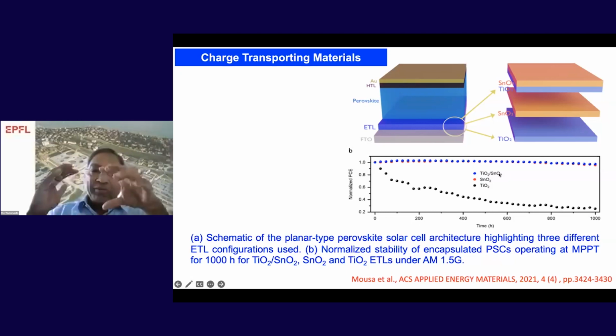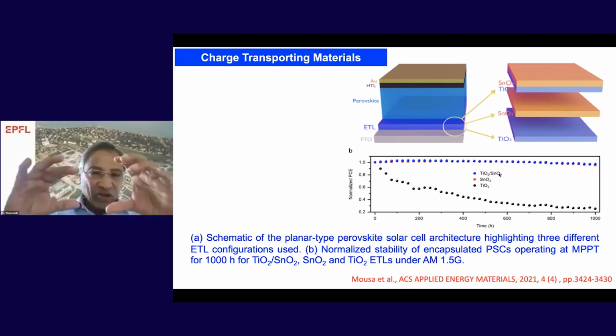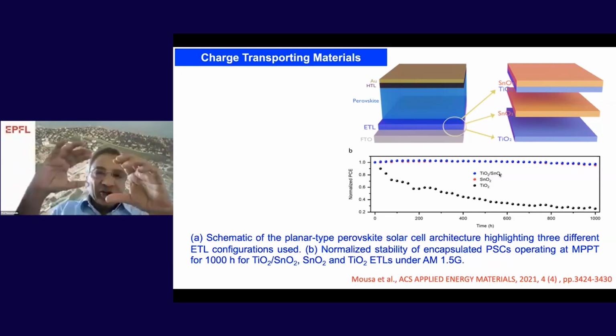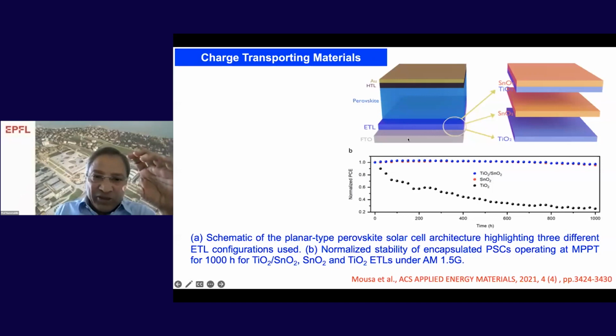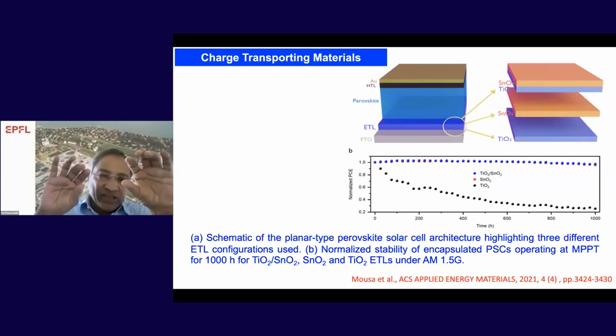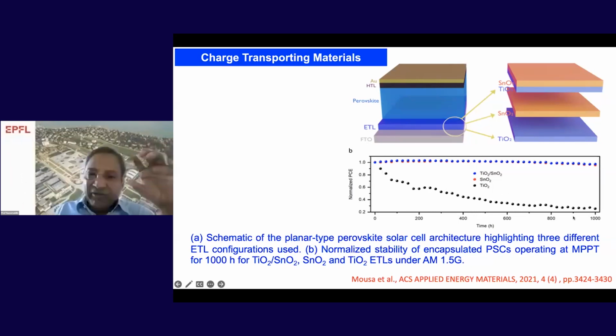So what is happening here is that when we have pure TiO2 as the electron transport layer, we deposit perovskite on top of the ETL, and when the light is passing through the TiO2, which is a photoactive material, it forms holes at this interface. So the formation of holes followed by delamination is the main problem that is decreasing the efficiency. However, if we passivate the TiO2 or just replace TiO2 by pure tin oxide, you can see the intact efficiency because of the reduced activity of the interface between the perovskite and the ETL layer. So the delamination has reduced significantly.